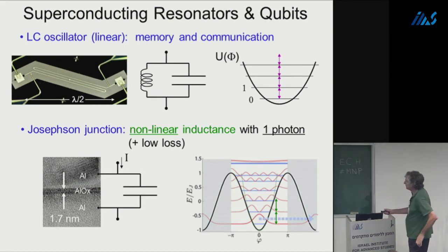And you work out the physics, it's also very low loss, just like superconductors are. So a Josephson junction is just two aluminum metals separated by a natural barrier of aluminum oxide. It's made with E-beam evaporation and just bleeding in oxygen, very simple. This is thin enough so electrons can travel through here. And this forms a nonlinear Josephson inductance, okay?